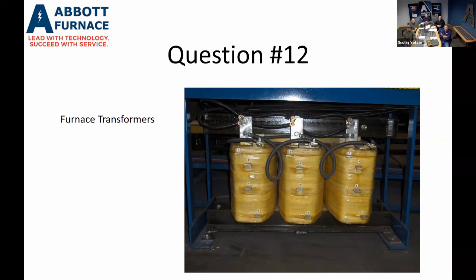That's one of the telltale signs of glow bars being mismatched or imbalanced. Then if you determine that your load is balanced and you're just not pulling enough amperage, then you can go up a tap, and you just take each one of those legs, those lugs right there, and move it down to the next tap. You want to make sure that you do all 3 banks the same, because this is a 3-phase system. They're not separate phases.